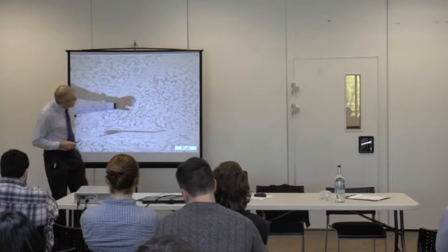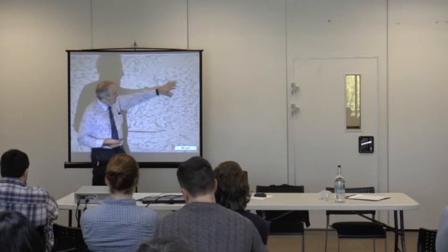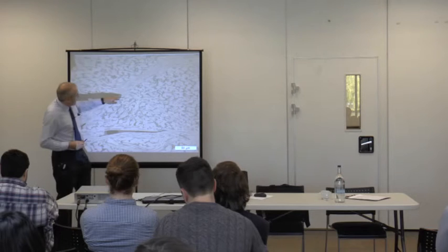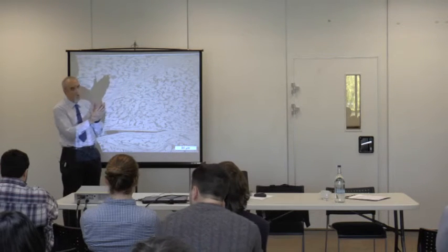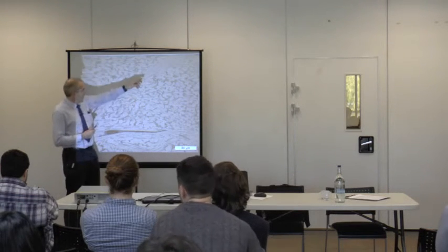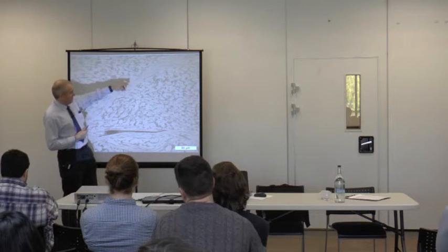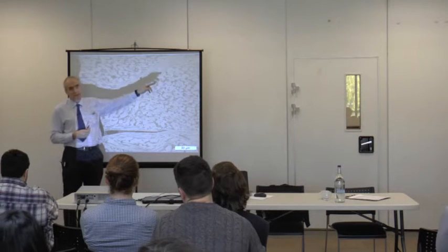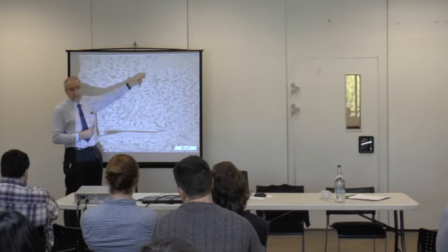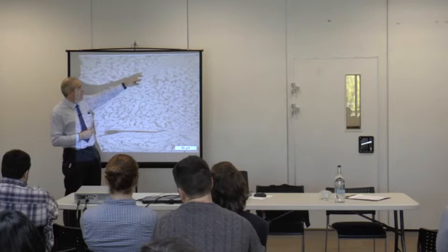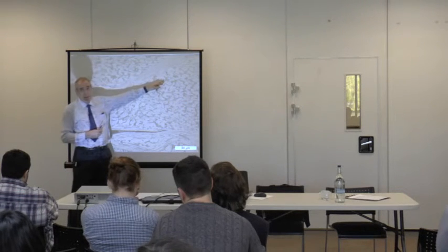And what you can see here, this is normal structure in our titanium alloy. And what you've got here is bands where it's started to deform, and because it can't dump the heat, you can have bands in here that are only tens of microns across where the metal can actually go molten in a band about 10 microns wide. Over here, it's completely unaffected.